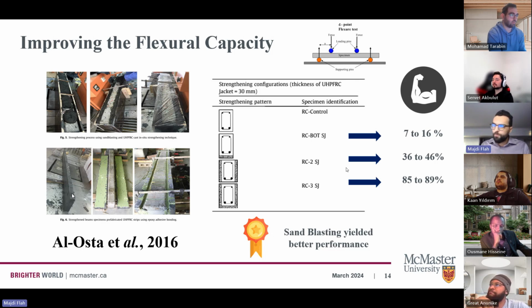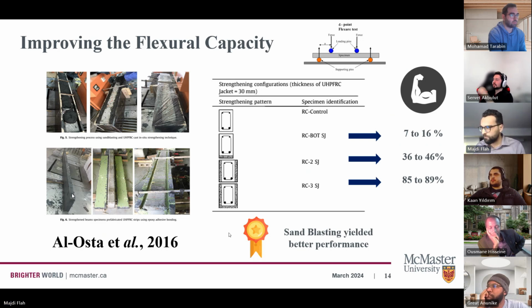The first one tried to put the layer at the bottom, as we did in our experimental study, the second one from the sides, and the third one is going to be like a U jacket, you know. So we can see that there is a lot of improvement, from 7% up to 89% for the three-side jacket. And here the authors tried to compare between sandblasting and epoxy adhesive bonding. And of course, sandblasting yielded better performance.